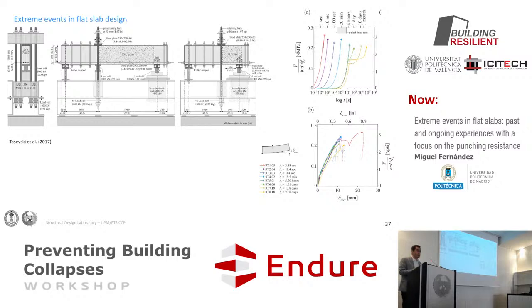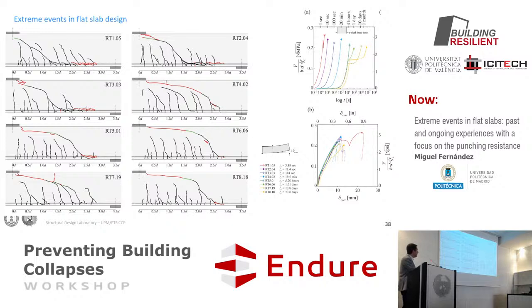The difference is in the shape of the cracks. And then you see it here. This is a very fast loading, and this is the shape of the critical crack, which is that one. And as you see, it is very low. While when we are doing long-term loading, even some days or some hours, what you see is that the critical shear crack is not that one. The critical shear crack is starting far away, and it's rather consistent. So the critical shear crack is shifting. And so while here, after the first crack, you could still have a direct strut, then you cannot have it in the other cases.